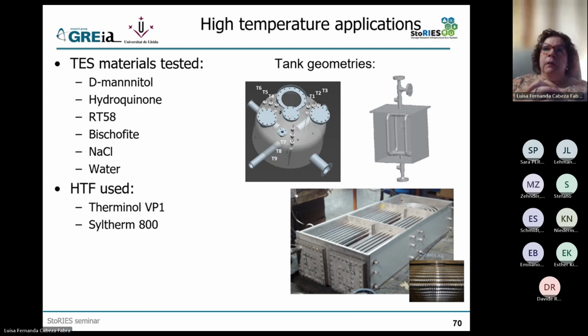And then one of the materials scientists that I had at that time in the lab told me, Luisa, let's look in the literature. And we found out that the mannitol actually, depending on the behavior of the material, could have 3 different peaks at 3 different temperatures. And depending on how you heat and cool this material, you can have only 1 peak or 2 peaks, or even 3 peaks, okay?